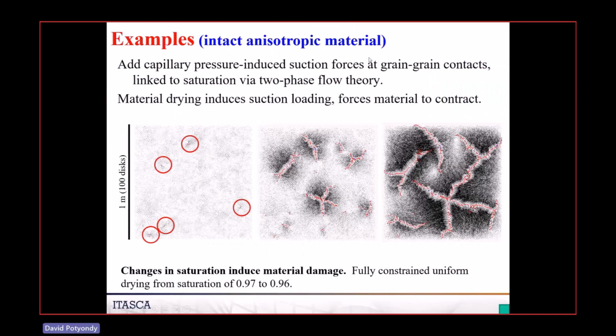This is just an example of some earlier work where we put in suction forces at the contacts, and we link that to the amount of saturation in the system by means of two-phase flow theory. Then you can take that system and start drying it out. As you start drying it out, you start increasing the suction. And that's what we're seeing here.